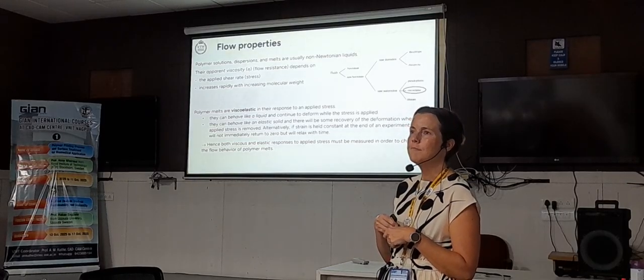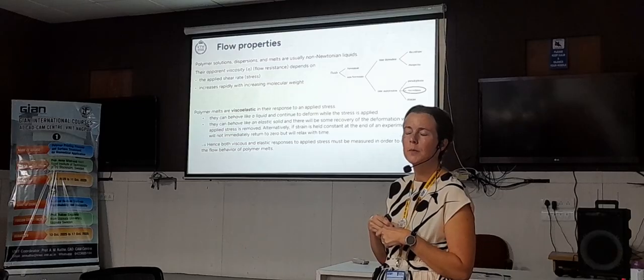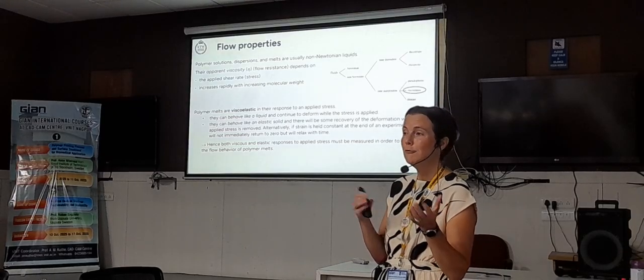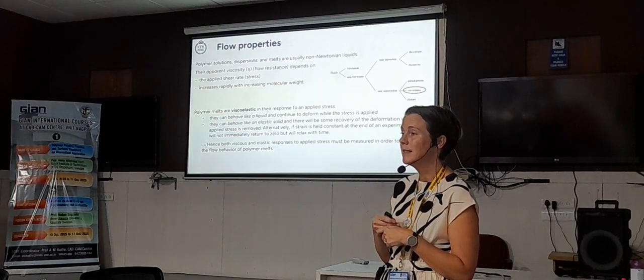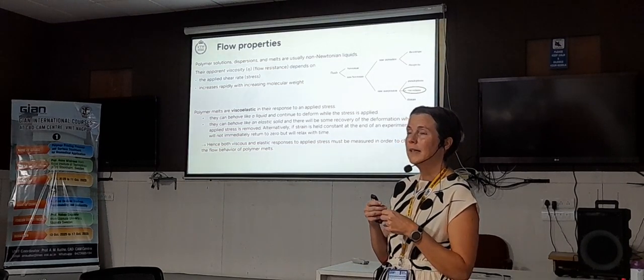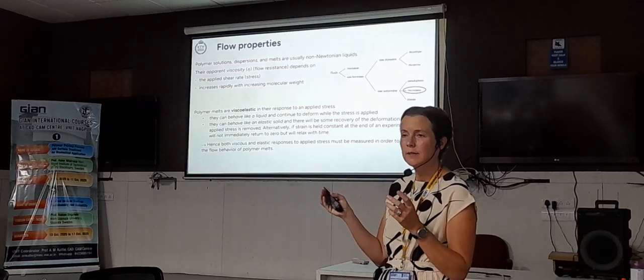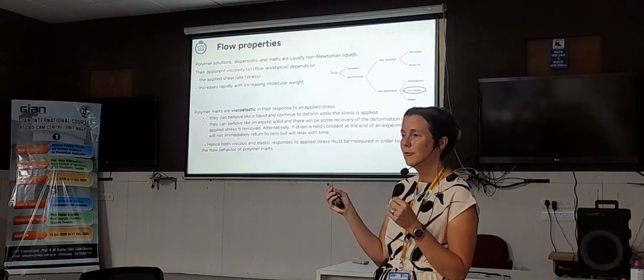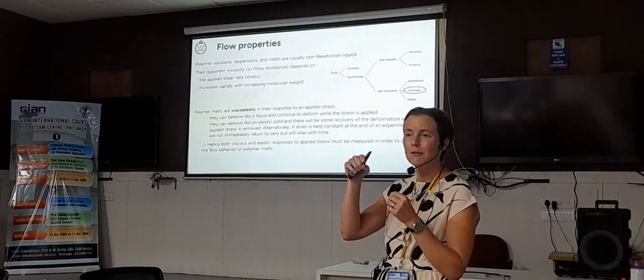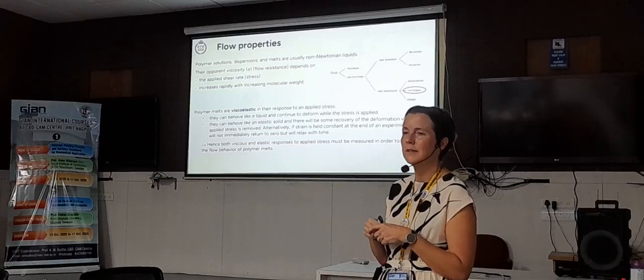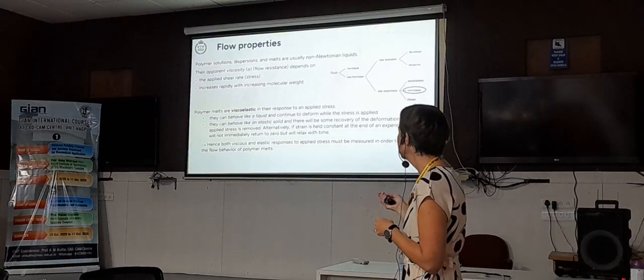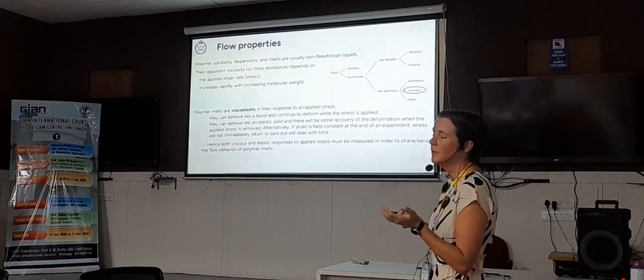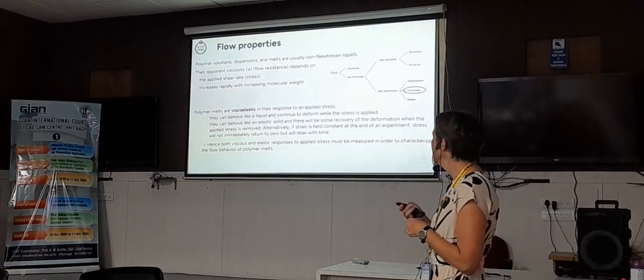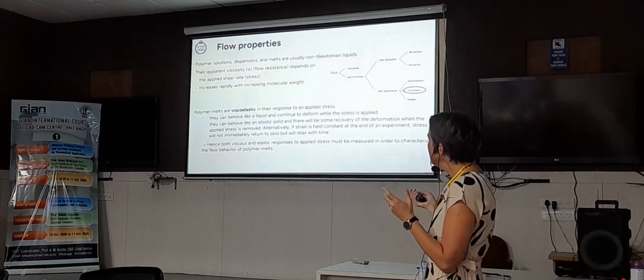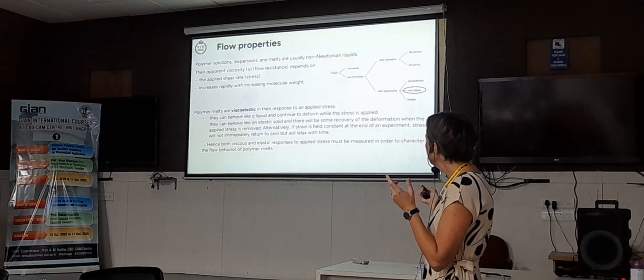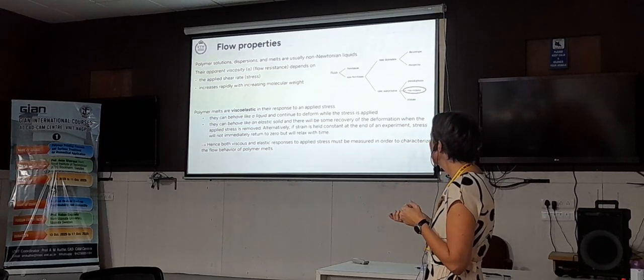And also, if you have tried to print polycaprolactone and compare it to polylactide, you know the difference between the melt elasticity, where the polycaprolactone is, even though it's in some way easy to print, it also has a high melt elasticity. So it can, in the nozzle, actually curl, and it can be difficult for it to start to print and adhere. And that is related to the melt elasticity in comparison to polylactide that has a lower melt elasticity. So we need to also have in mind that it's non-Newtonian and also that the polymer is viscoelastic.